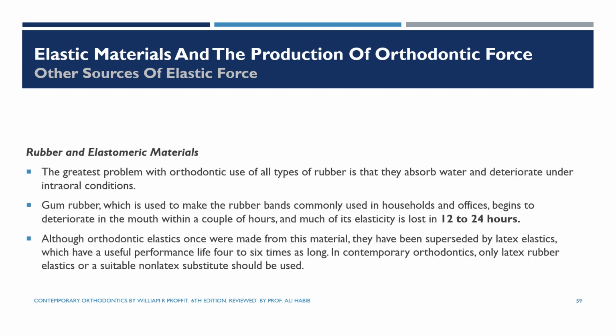An important problem of rubber is that it absorbs water and deteriorates under intraoral conditions, especially the gum rubber that is used to make household and office items, which was found to deteriorate in the mouth within a couple of hours, and sometimes it loses elasticity in 12 to 24 hours.